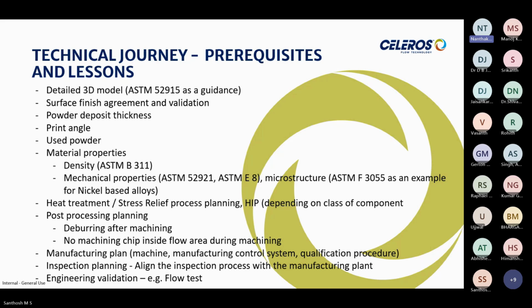But if you read the standards that are coming in recent days, the HIP is being covered. If you look at the standards, they talk about different classes, and they say you can stress relieve and then do an HIP. And from the studies which are coming in recently, and also Wipro has confirmed that study, the material properties are better than that of castings, and very close or equal to that of forgings. So we are talking about metal printed parts which have properties better than castings, and properties which are close enough to forgings actually.